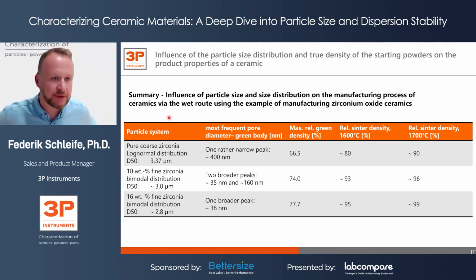So to summarize this a bit, I could show you that when you use the pure coarse zirconia with a log normal distribution of around 3.4 micrometer, you might get in the green body one rather narrow peak for the pores at around 400 nanometer, but with the relatively lowest green density, lowest sinter density, either at 1600 or 1700 degrees Celsius sintering temperature. By increasing the ratio of fine zirconia up to around 10 weight percentage, we got a bimodal size distribution with a D50 of around 3 micrometer. And for the pore size distribution in the green body, we got a bimodal distribution. So we got small pores and larger pores, resulting in medium green body density and sintering densities.